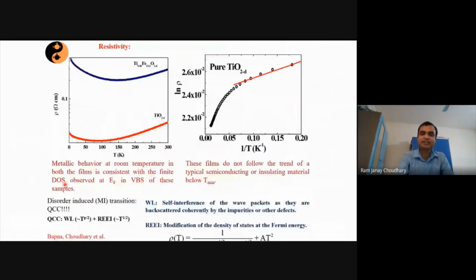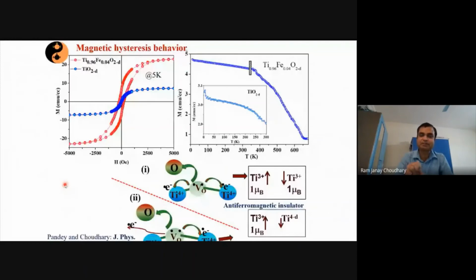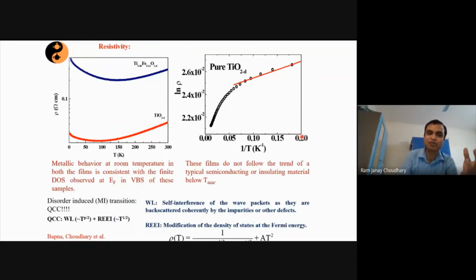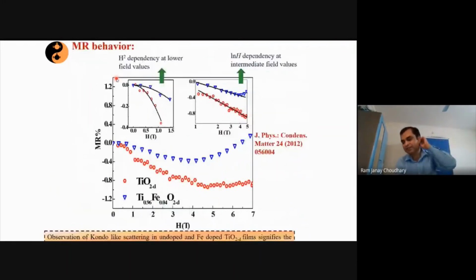So from there we get an idea that the iron which you are doping in this system is substitutional in nature, because your structure was also single phase, and your charge state was showing 2 plus, 3 plus, not an indication of a metal cluster. Now this is the magnetic property. You can see that the system shows a very good, clear-cut hysteresis behavior. So from there we know that the system has started showing magnetic behavior. Its Curie temperature is also way beyond 600 Kelvin. So we know that the purpose of doping iron in the system is justified. The system also shows very low resistance behavior, with high temperature metallic behavior and low temperature semiconducting behavior in TiO2. So if you apply a magnetic field, since the magnetic interaction is taking place via charge carriers, then under the application of a magnetic field, the resistance of the material also changes.